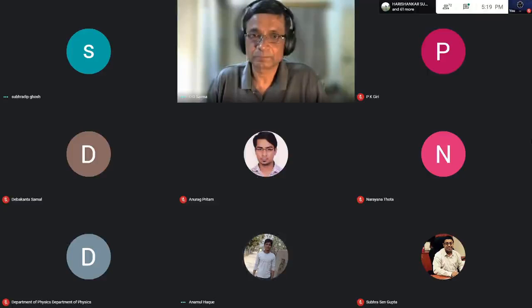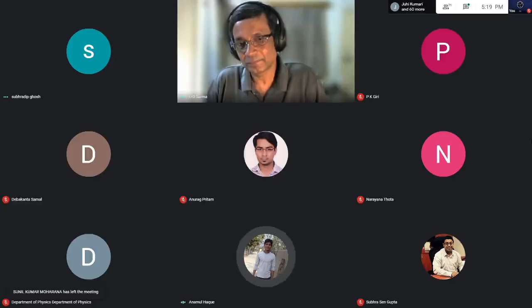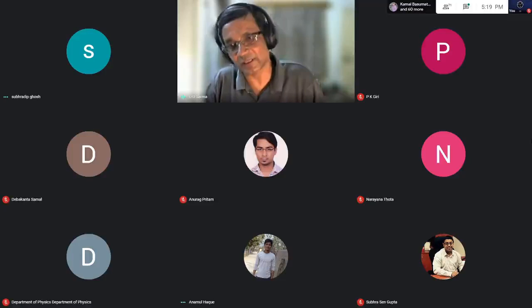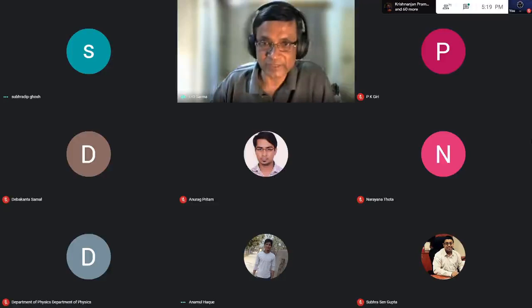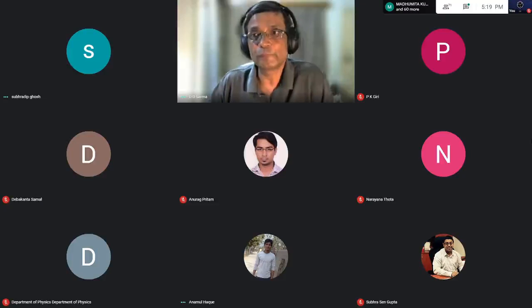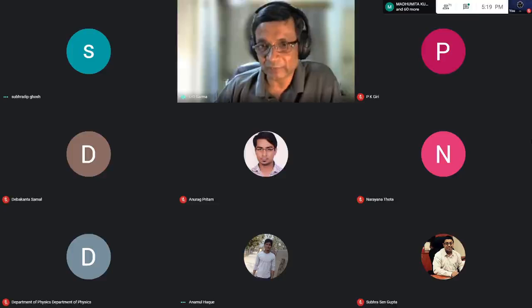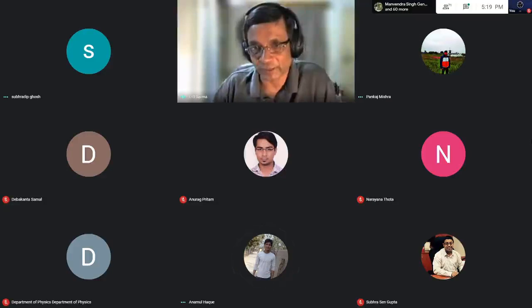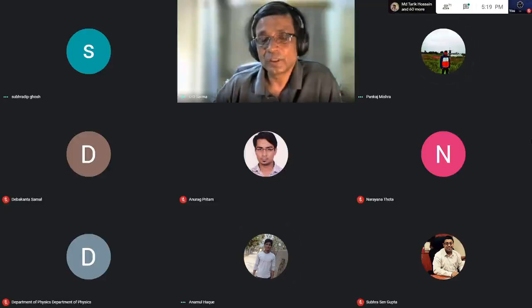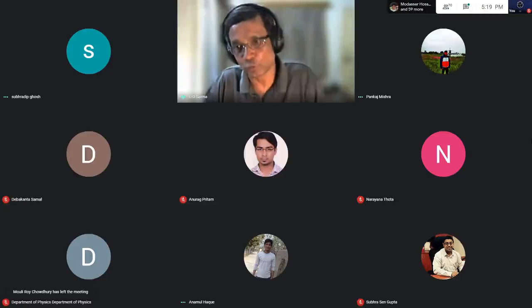Sir, I have a doubt. You are doing the measurement below room temperature, and room temperature also, depending on what we are doing. So these are in orthorhombic phase. I have shown you data for all temperatures: orthorhombic phase, tetragonal phase, cubic phase for crystal structure, X-ray diffraction. I have shown you PE loop measurement, both at 77 Kelvin, which is orthorhombic phase, as well as room temperature, which is tetragonal phase. I have shown you dielectric measurements, which show that it's not ferroelectric, over the entire temperature range. I've shown you SHG at room temperature.